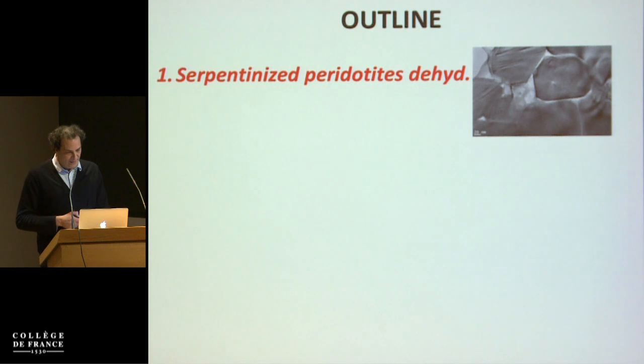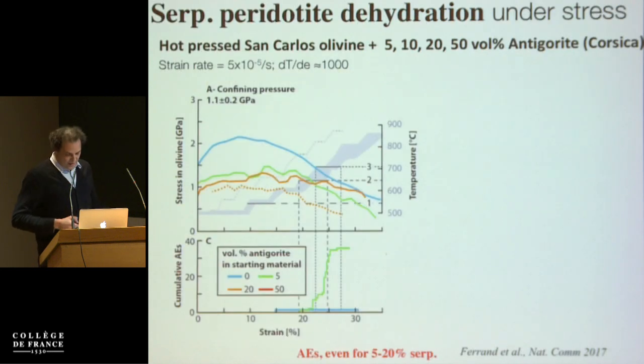So in serpentinized peridotites, we've been working on hot-pressed San Carlos olivine, which is the high-pressure physicist's olivine, to which we add 5, 10, 20, or 50% antigorite, which is the serpentine mineral. And we did experiments at a regular strain rate. This is the increase of temperature as a function of strain rate. So the temperature rate as a function of strain rate is around 1,000, which is comparable to what you would expect for a typical slab.